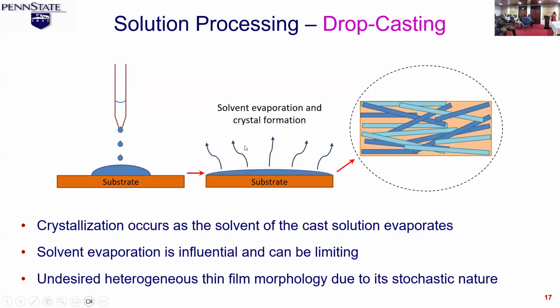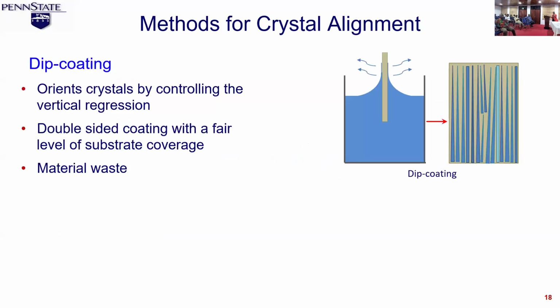Then what happens is that for drop casting, you just allow the solvent to evaporate. When it evaporates, it crystallizes over time. But with drop casting, because you are not really directing the crystallization, it crystallizes whichever way it wants to, right? So some methods have been generated to get over the challenges you have with drop casting. One is dip coating, where the substrate is dipped into the TIPS-pentacene solution and then is drawn out of the solution gradually. As it's drawn out, right at the top, your solvent evaporates, so as it's drawing out, it starts to crystallize. So you will end up with pretty well-oriented crystals.